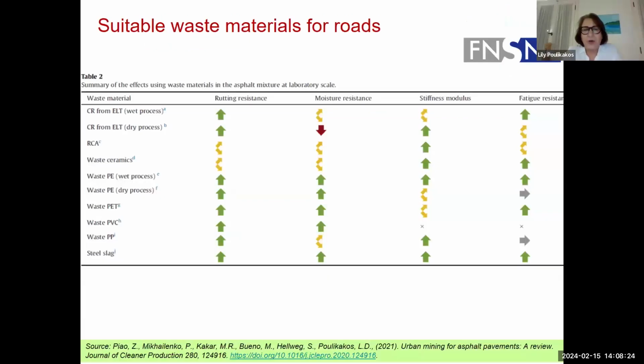Now we have published some papers about what the experience with alternative materials is within the available literature. And here I have some samples of the waste materials in the left column, and we've looked at rutting resistance, moisture resistance, stiffness, and fatigue. And we see that many of these alternative materials can perform better or similar to all virgin materials. And with the upward facing arrow, we're showing this. So basically what we see in the literature, what our colleagues have shown, is that it's possible to use these types of materials.